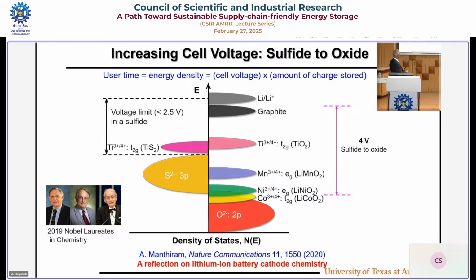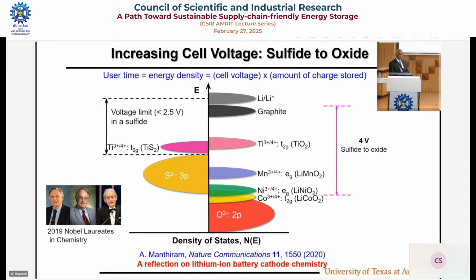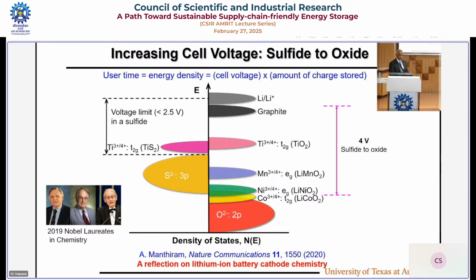Anyway, so that changed. Because this is at a lower energy, you suddenly have access to higher oxidation states like cobalt 3 plus, 4 plus or nickel 3 plus, 4 plus. Cobalt 3 plus, 4 plus, you cannot have access to in a sulfide. You can never, because as the oxidation state increases, the energy level will keep on going down. Remember XPS, binding energy will increase with increasing oxidation state. That means with increasing oxidation state, the energy level is lower. So it's the same thing. That's why I say chemistry and physics are inseparable.